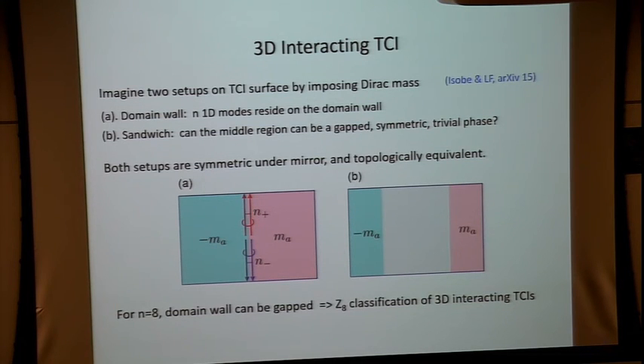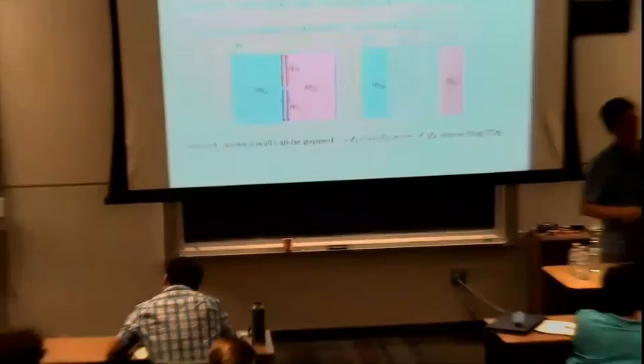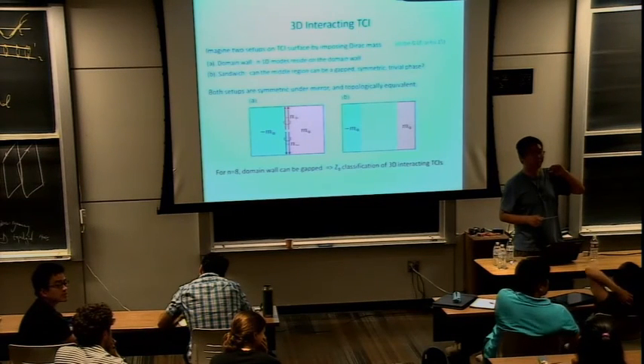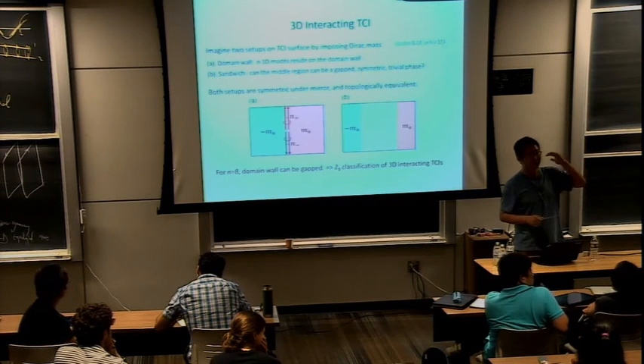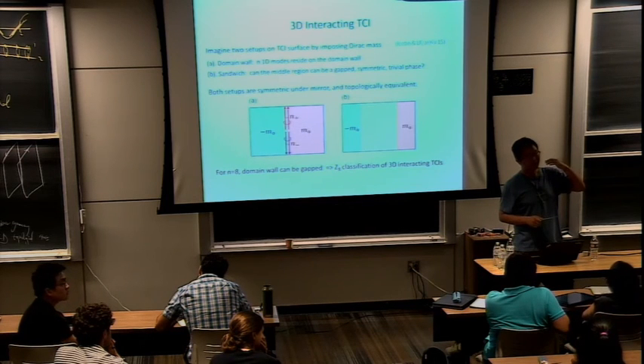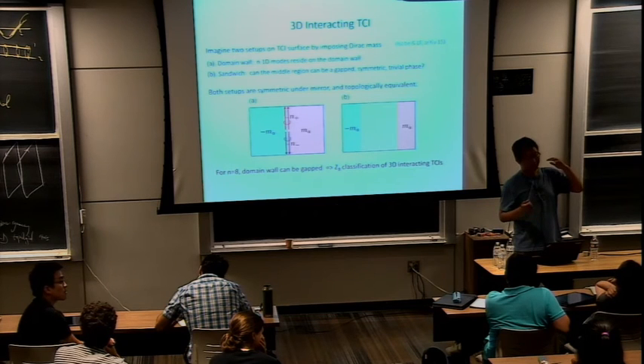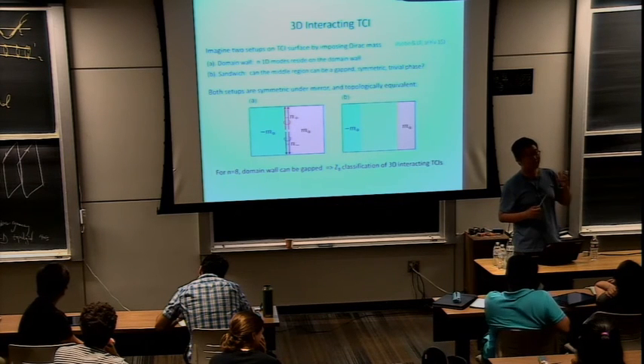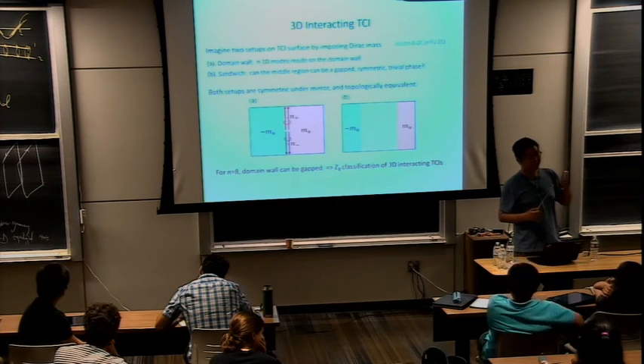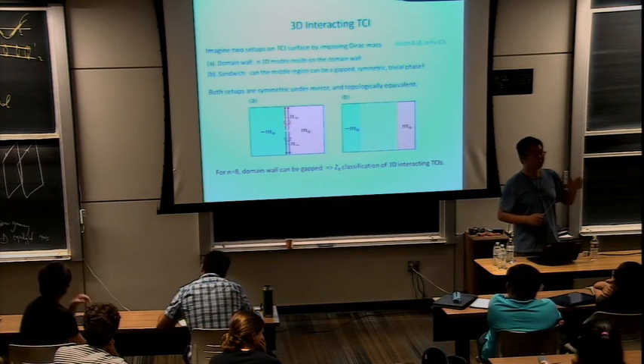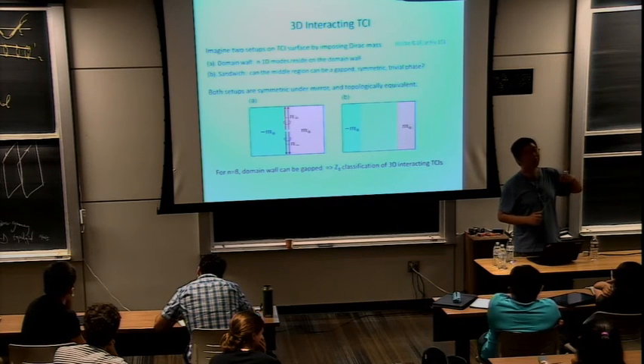Yeah. So we could put disorder in the bulk as well, but the argument goes as follows: we first think about whether the surface states can be localized in the presence of disorder. Then what I've argued is that even at sufficiently strong disorder, the surface remains metallic, right? So this tells us there are delocalized surface states, even in the presence of strong surface disorder. So this implies that the bulk is a topological phase.